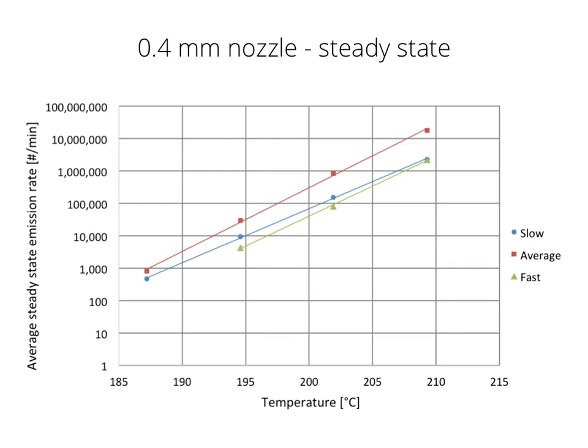However, I tried to do an experimental run also with a contaminated nozzle and heater block, where there was some residual filament on there, but the problem was I couldn't get repeatable results. You get very high emissions from these contaminated heater blocks, but they are not consistent. If you run it the first time, you get maybe a few 100 million particles a minute, and then the second run you would only get, let's say, 50 million particles a minute, and then the third run would be only 10 million particles a minute. So the burning off of the filament over time will emit less and less particles.